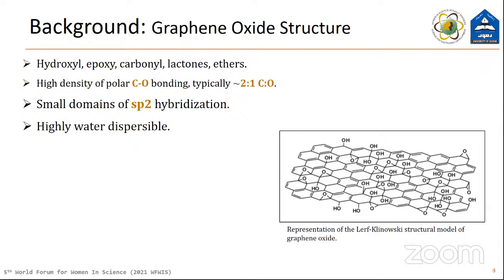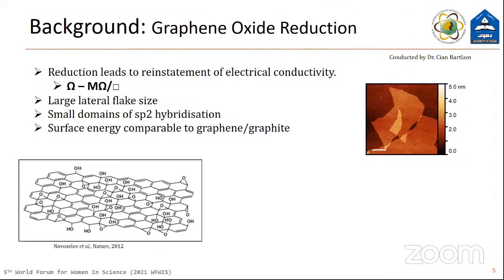charge stabilize the dispersion. Typically, the concentration of the aqueous graphene oxide dispersion ranges from 1 to 4 milligrams per milliliter, but can go even further. One of the important properties of graphene oxide is that the pi-electron structure of the graphene basal plane can be partially reinstated by reduction or washing of the oxygen moieties, which leads to the production of reduced graphene oxide and an increase in electrical conductivity. Whilst complete reduction of graphene oxide to pristine graphene has yet to be achieved.